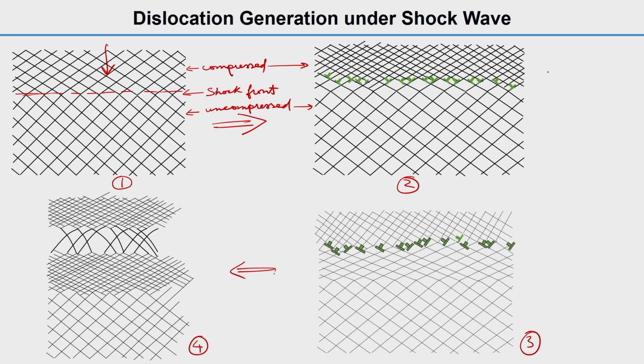So, what happens here, the dislocations are generated here, but first I just need to tell you that for uncompressed material this lattice was cubic. By now you have understood, these lines we are drawing are the lattice, the atomic planes, and here the lattice in the compressed region is monoclinic, because of the deformation. So, here it is cubic in this region, and here it is monoclinic.